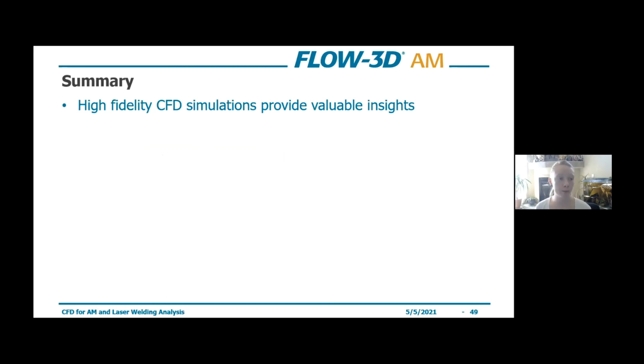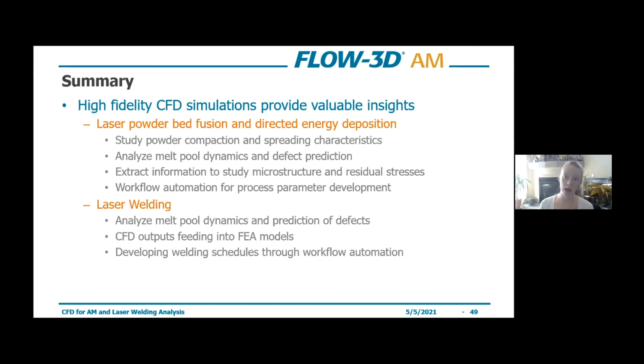So in summary, we've really found that CFD simulations are providing valuable insights into these processes, and that relates to both the AM side of things, laser powder bed fusion, directed energy deposition, as well as laser welding. In the case of AM, you want to look at powder compaction, spreading, powder interaction. In both cases, you want to look at melt pool dynamics, prediction of defects. We want to extract relevant information to use in subsequent models such as microstructure prediction, residual stress analysis. And then using workflow automation, we can develop these process parameter windows or welding schedules in a very efficient manner, where we're able to tie it all together and provide some valuable insights into how to bring these processes into production.